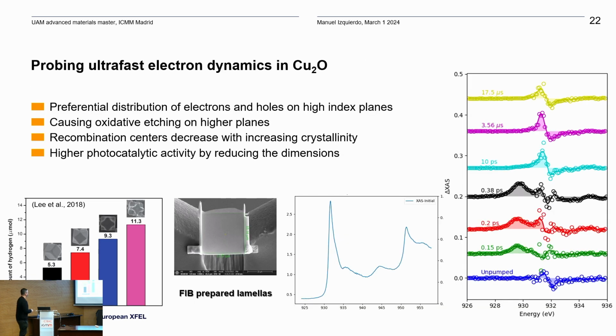You can even give a second twist to the technique of TR X-ray absorption spectroscopy, and you can decide, okay, the measurement with the microtome was not fantastic, can I do better? What you can do is take a single crystal and prepare a lamella, which again has to be on the order of 100 nanometers thick, and we have done this in cuprous oxide, which is a material that is relevant for catalytic applications. One of them is hydrogen production, and what is known is that a specific high-index phase has different reactivity. And the higher the index, the higher the reactivity.